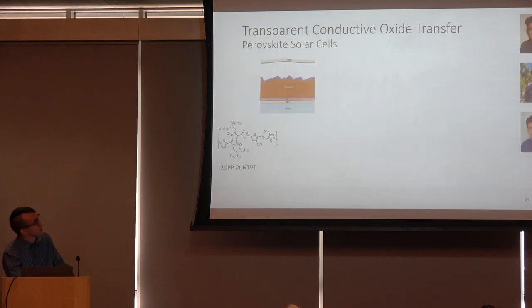And lastly, this brings us to our current attempt. There's work left to be done, but our current attempt at incorporating these films into some perovskite solar cells. We built up some almost completed half cells with the help of Dennis Kakan, and additional film preparation was done with the help of Jaden and Ben. Essentially, we prepared these perovskite cells, finishing off by spin coating this electron transporting polymer, 2DPP, 2CNTVT.